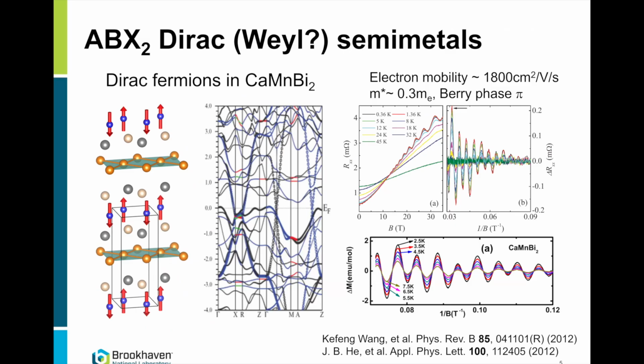However, soon afterwards, the Weyl splitting was postulated in a similar system, a material, calcium manganese bismuth 2. So we replace ytterbium with calcium. Again, quantum oscillations, tens of Kelvin, high mobility, low electron mass. So here is Shubnikov, here is de Haas-van Alphen, here is Shubnikov-de Haas. You see all sorts of quantum oscillations. Very similar structure with bismuth layers and intervening manganese layers ordered with, again, very similar magnetic moment, about 4 Bohr magnetons.